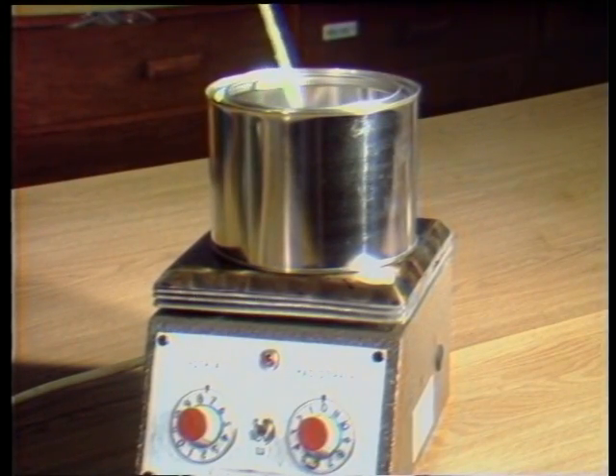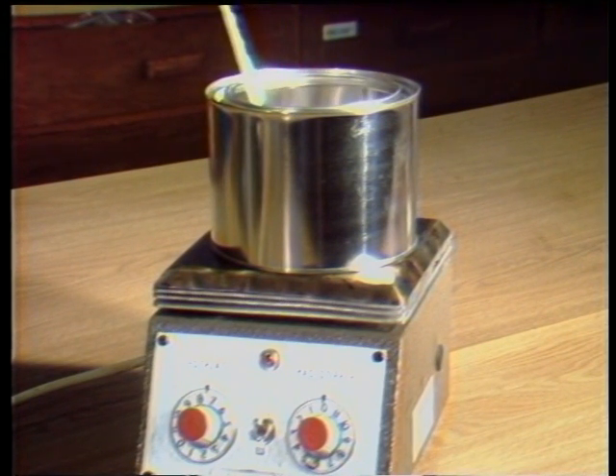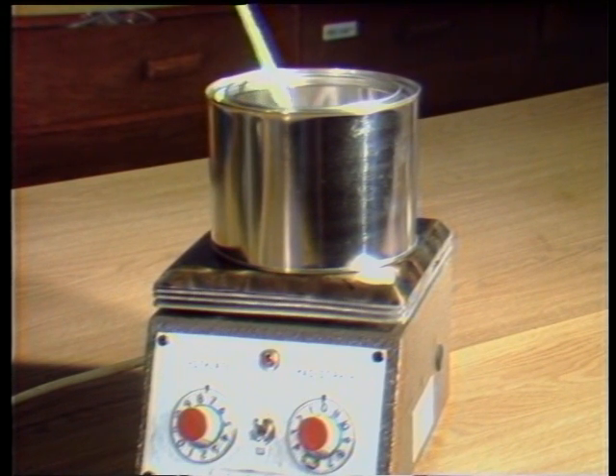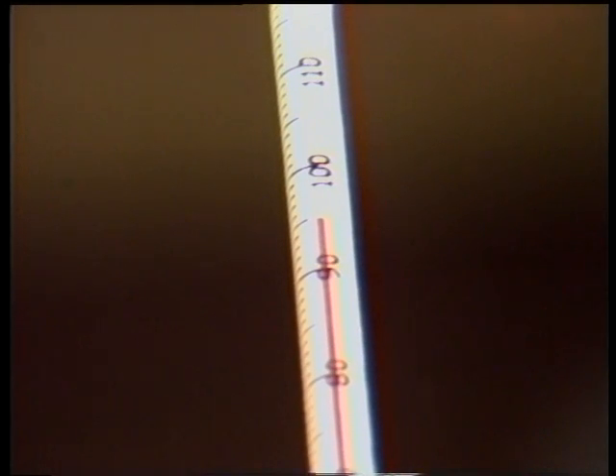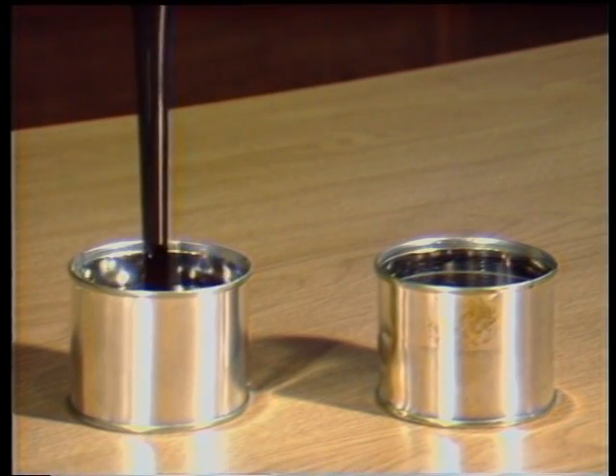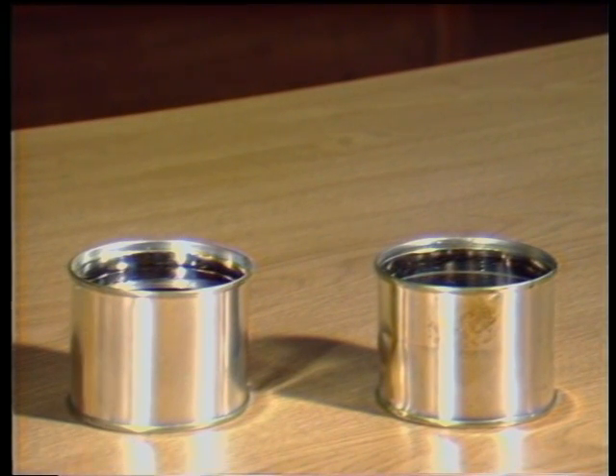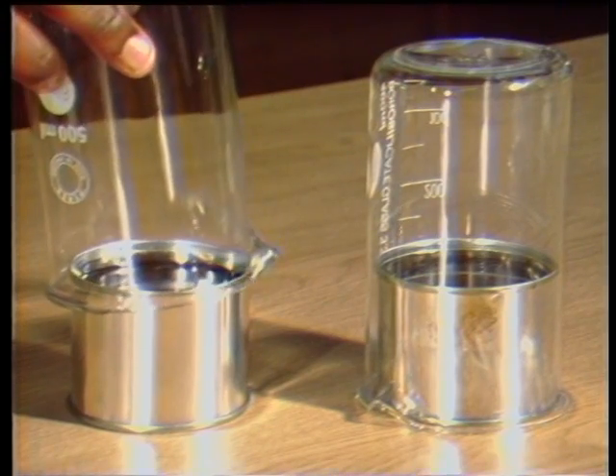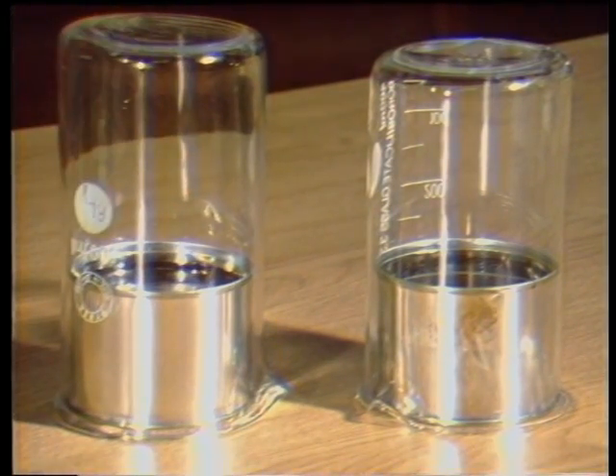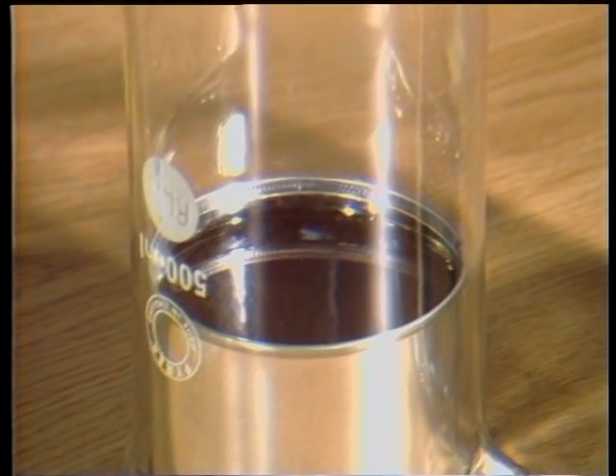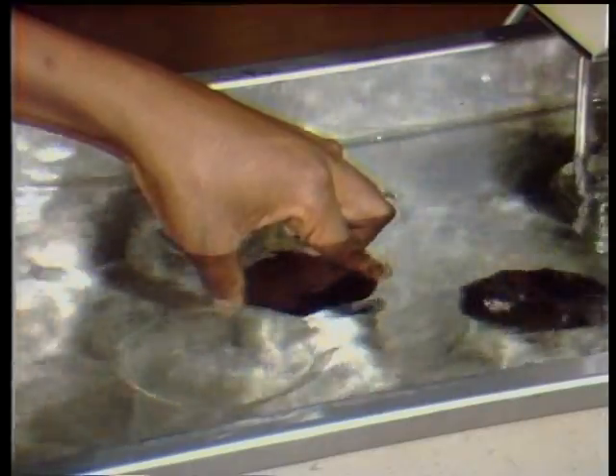Preparation of the sample. Heat the field sample in an oven or on a hot plate with great care, stirring when possible to prevent local overheating until it has become sufficiently fluid to pour. In no case should the temperature be raised to more than 90 degrees Celsius above the expected softening point of the bitumen. Fill 2 specimen containers to a depth of at least 10 millimeters greater than the expected penetration. Cover the specimen container with a lip beaker for 15 minutes to assist in the elimination of trapped air bubbles. Allow the specimen to cool at room temperature for an hour and a half. Place in the water bath at 25 degrees Celsius for the same period.